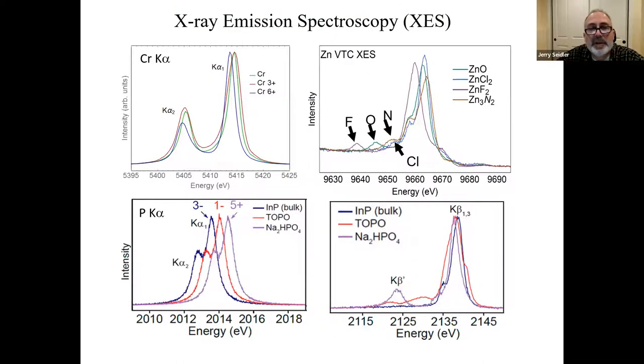So some spectra here, both for transition metals and for phosphorus. And you can see that there's a sensitivity in the K alpha emission of chromium to oxidation state. And for example, in this zinc valence-to-core study, the movement of this peak, often called the beta double prime peak, gives you a clear signature of the ligand in these different materials.